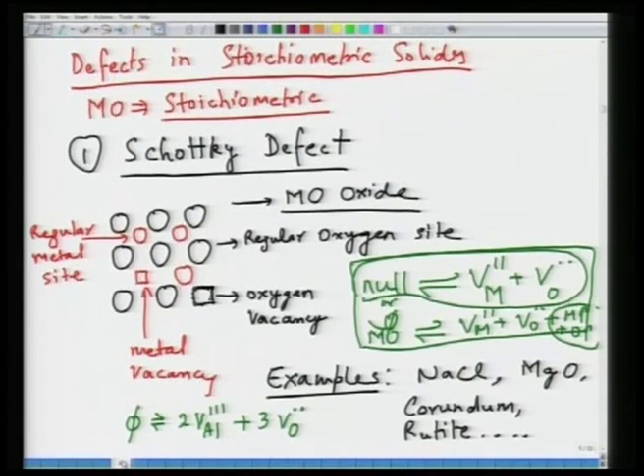And then we looked at what are the defects in stoichiometric solids, assuming the case of MO as stoichiometric solid. So the first important defect is Schottky defect. Schottky defect is nothing but formation of a metal and oxygen vacancy, simultaneous formation. This does not disturb the stoichiometry of the material. So basically you have a pair of two vacancies in a given solid. The relative proportion of these vacancies will change if you had materials like Al2O3 or TiO2. So I would leave it to you to work out, but make sure that you maintain the charge and site balance there.